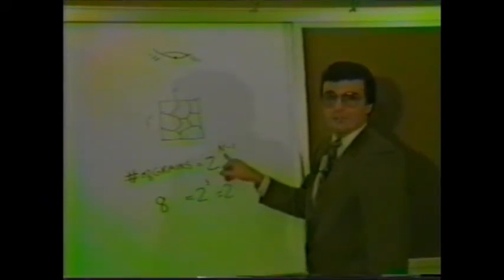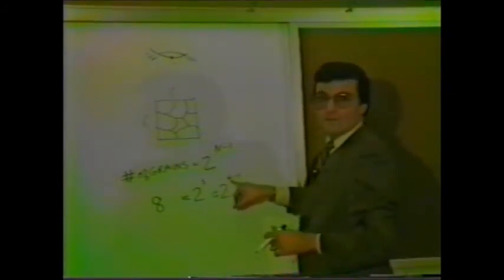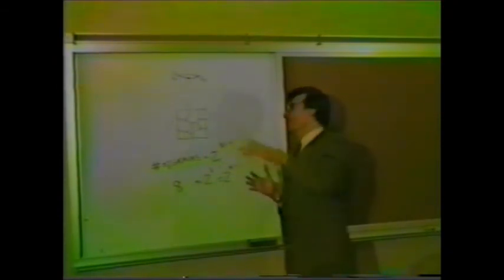So what all this says is that if the grain size number n is between 1 and 4, this is considered a coarse-grained steel, because relatively few whole grains would fit into 1 square inch at 100x. There is a term called fine-grained steel, at which this number is 5 to sometimes 8, or generally it's called 5 and finer, that maybe you could have even 1,000 grains in 1 square inch viewed at 100x. So, just to repeat, when the grain size number is 5 or finer, and sometimes it's specified as 5 to 8, this is considered fine-grained steel. When the number is 1 to 4, then the grain size is considered coarse grain steel.